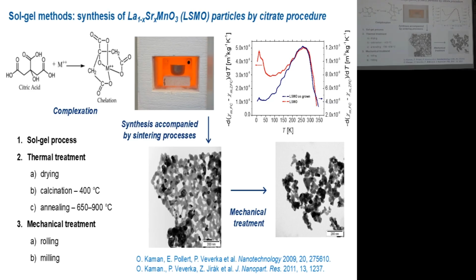Actually, we were interested very much in particles of this phase, and we were trying to find some alternative procedure, something more sophisticated that would enable us to achieve better control over the shape and over the distribution of sizes. So we tried to prepare these particles in flux. It means in some molten salt or in molten hydroxide, and at the end we were somehow successful while preparing these particles in molten sodium nitrate.